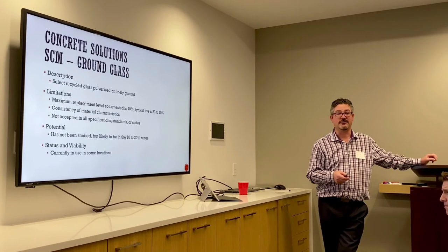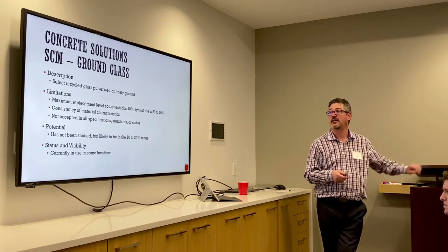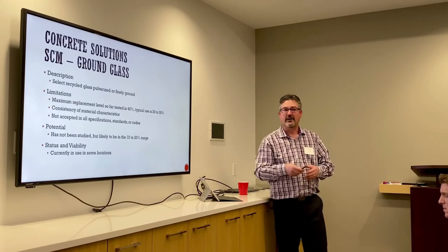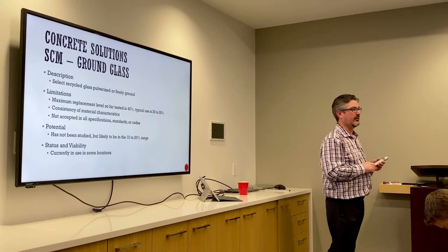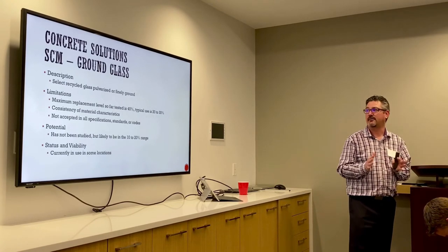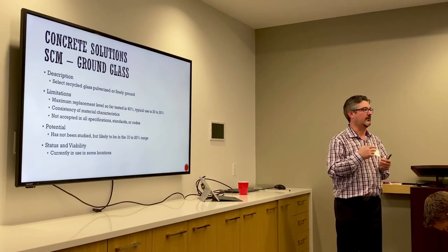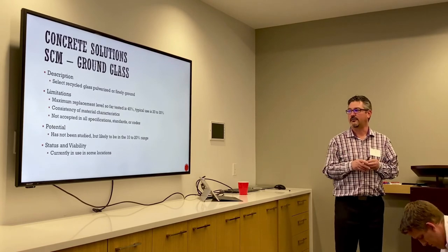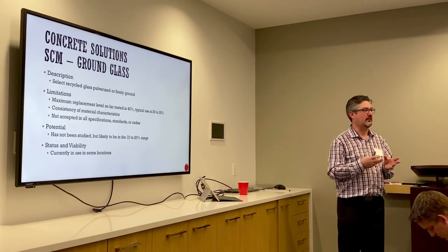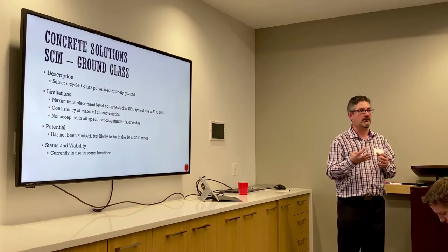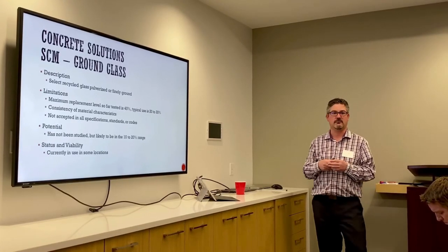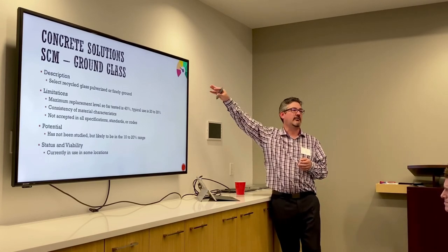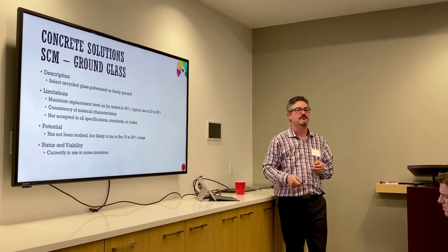Ground glass, this is relatively new. It's recycled glass, pulverized and ground down into a fine powder. Relatively recent, so far the maximum that's been tested with this material is 40%, so typically in the 20 to 30% range. You've got to be aware of how consistent the material is. Again, not accepted in all specifications, standards and codes. Potential hasn't really been studied from an LCA perspective, but probably somewhere in the order of 10 to 20% reduction. Currently available in some locations, I rate this relatively low because its availability is so limited.